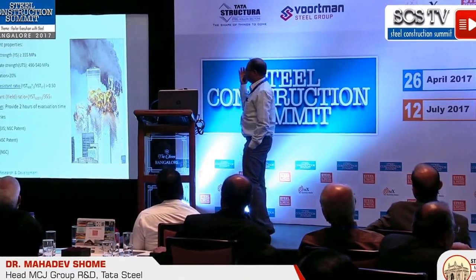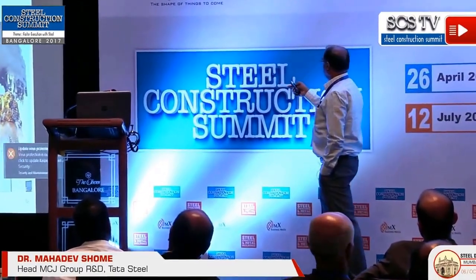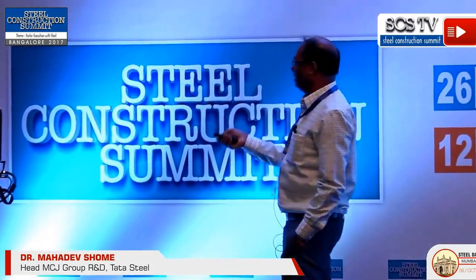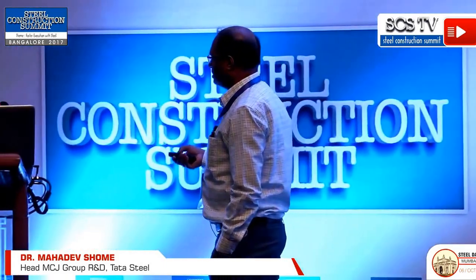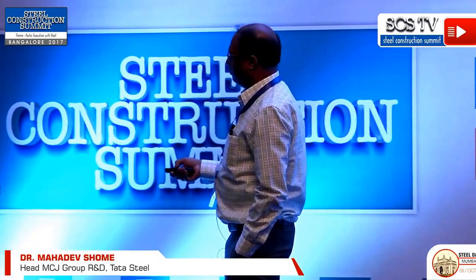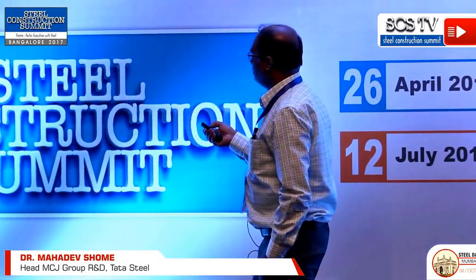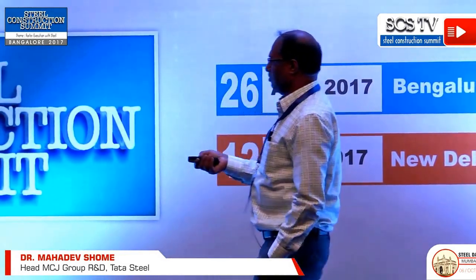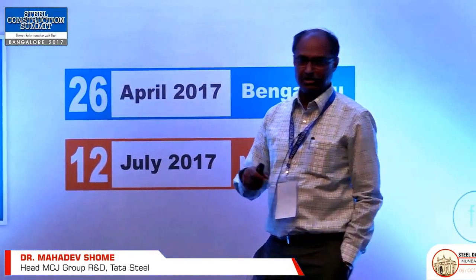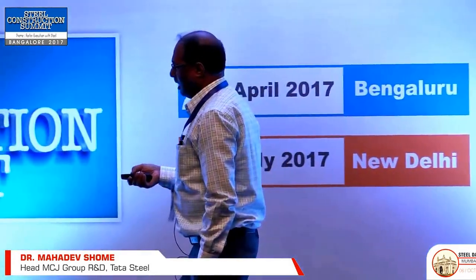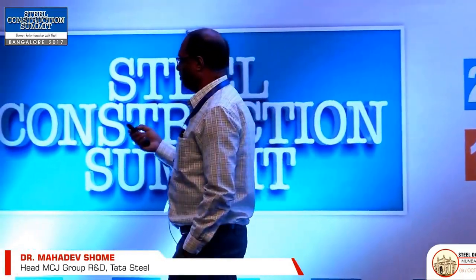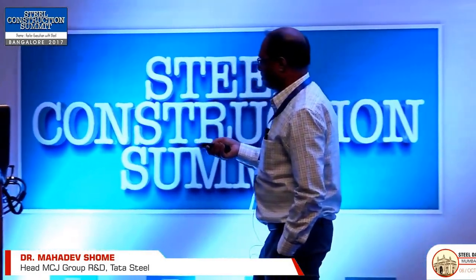So, we today supply, as part of this Tata Structura, the YST 310 and the 355 grade of steels, which have these properties. But what is an add-on which we have recently developed and would like to introduce to this Tata Structura is the fire resistance aspect. And we are talking about fire resistance ratios, which is the ratio of the yield strength of the material at 600 degrees centigrade, in case of a fire, and at room temperature of greater than 0.50. Now, I'll tell you about the plain carbon steel and then get into the fire resistance development.